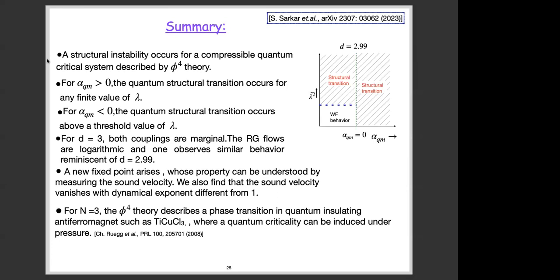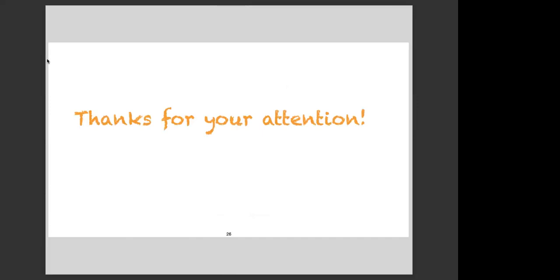And for d equals exactly 3, I think both of the couplings are marginal and the flows are logarithmic, but one observes similar behavior, reminiscent of the 2.99 dimension. With that, I would like to conclude. Just a side comment: n equals 3 actually describes a quantum insulating antiferromagnet, thallium copper chloride, to give you a physical system described by this n equals 3 phi^4 theory. But no structural transition has been observed so far, so this is purely theoretical. With that, I would like to thank you for your attention.